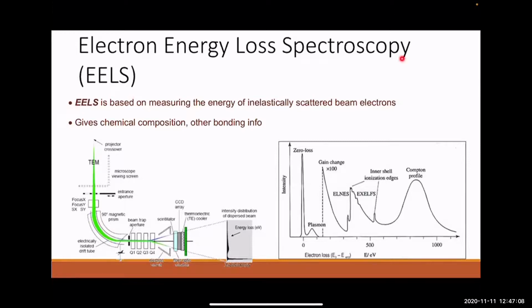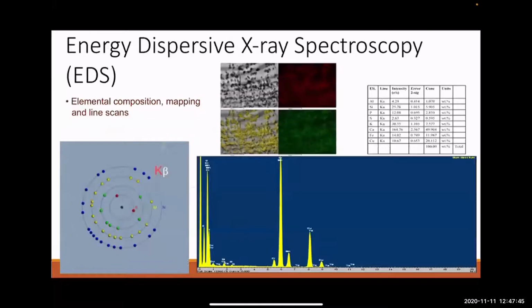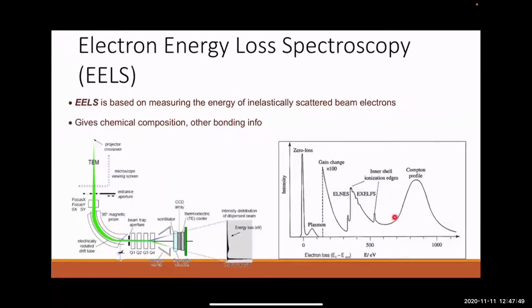But there's something called EELS, which stands for Electron Energy Loss Spectroscopy. I know this is a complicated looking diagram, but essentially what it's doing is, with TEM, your electrons come in, and if one scatters off your material, if you could somehow measure how much energy that electron lost, then you could work back how it must have scattered. For example, it must have scattered off a carbon atom because it lost this amount of energy, or it must have scattered off a copper atom or whatever. So you can get a spectrum in some ways very similar to what I showed before with the EDS, where you're measuring the energy of X-rays. Here you're measuring how much energy the electrons have lost if they've scattered through the material.